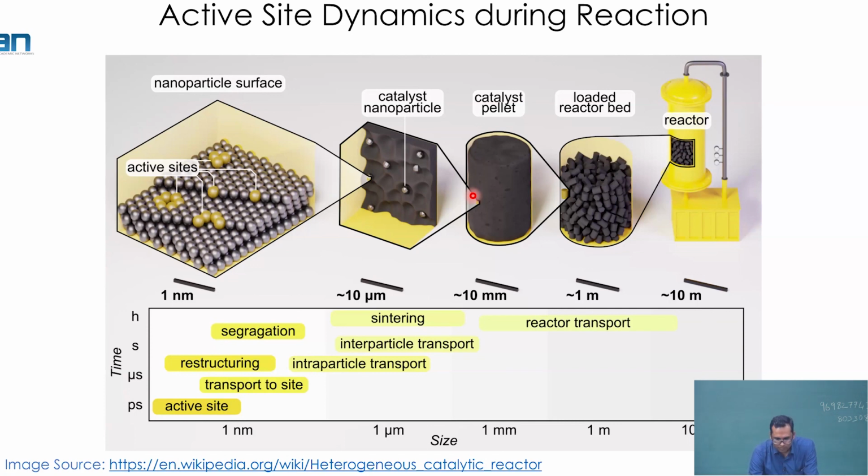So we took this copper zinc oxide alumina catalyst which is shown here, and then it was treated, or say reduced, in hydrogen environment for 60 minutes. And what we observed is that even after reduction in hydrogen environment for 60 minutes, we can see the copper nanoparticles and the zinc oxide particles are separated from each other, and they are coexisting on the surface of the alumina.